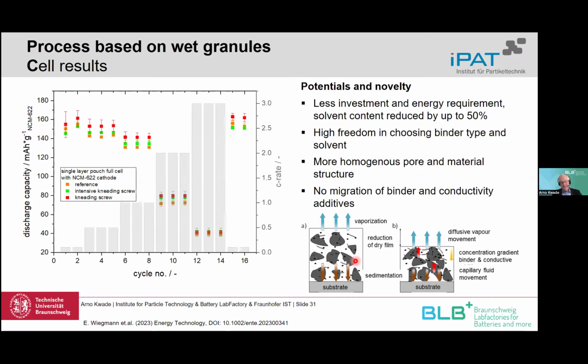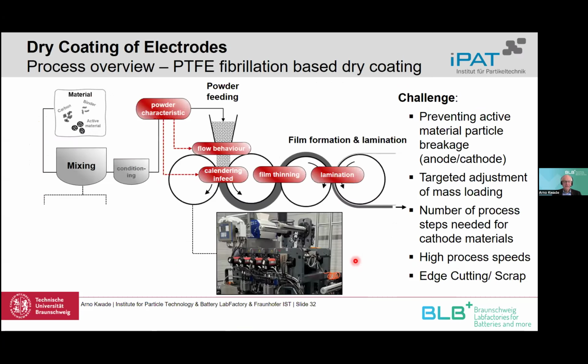But it's also not the case if we have a full dry process, which I show here. In that we have again a mixing process, but in this case a full dry mixing process. In the semi-dry process we have still some solvent. It's much less than saturated, so it's maybe 50% of the pores are filled with liquid. Here we have no liquid, and we have to mix the process, but we have to use a certain binder. I come to this, otherwise it doesn't work, to get a really nice mechanical strength of the electrode.